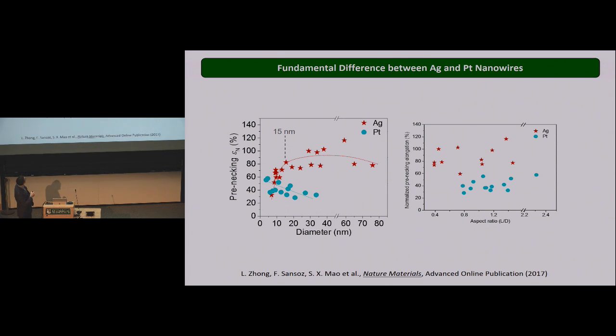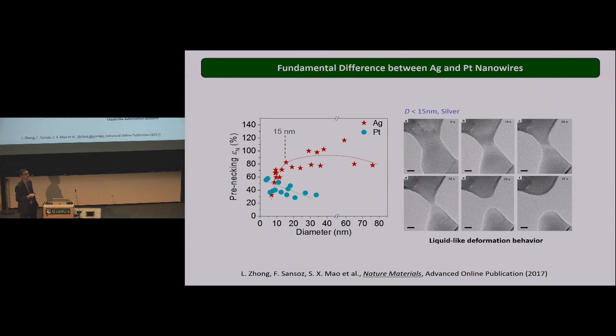But up to a certain limit, you see below 15 nanometers, the silver nanowire will find a significant softening. And actually that made sense based on the observation we made in the microscope. Below 15 nanometers, basically, without even applying any stress, this crystal would just deform like the liquid-like behavior. We don't even apply any stress here. The neck occurs naturally by diffusion from the surface and breaks that junction. Right? So that only happens when your crystal is less than 15 nanometers. But this range here, which was totally unknown so far, shows very different behavior.